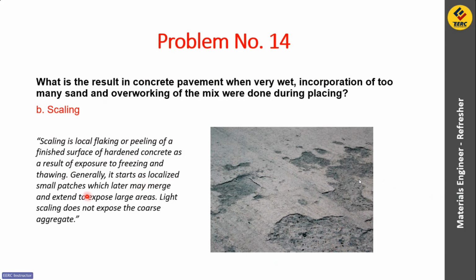Generally, it starts as localized small patches, which later may merge and extend to expose larger areas. Light scaling does not expose the coarse aggregate. It is only the topmost layer. So we will repair these kinds of problems or issues. First, we remove the parts that could still get damaged. We use a hammer to totally break off the parts that are like flakes. So we break those flakings first and then apply a surface sealer to correct our surface.